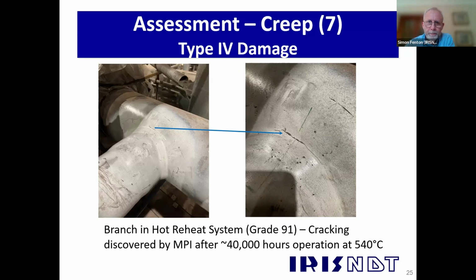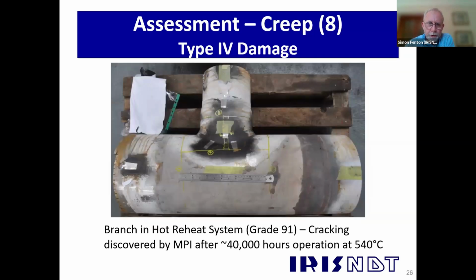Next slide, please, Pete. So this is the same branch after we've taken that particular branch out of service. We weren't able, because this was creep and the branch was so thin, it was about 10 millimeters in wall thickness, we weren't able to carry out a weld repair. If we do a weld repair with this, we have to remove all the heat affected zone. So that would have opened out the excavation too wide, given the thickness. So in this particular case, we had to rip out that T and put a new branch in place.